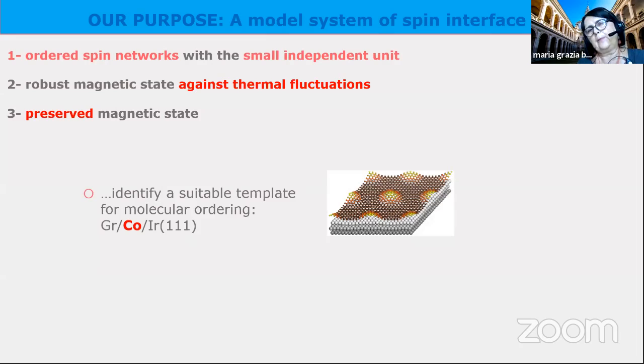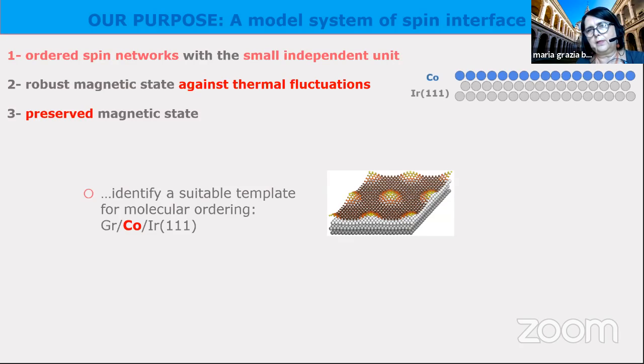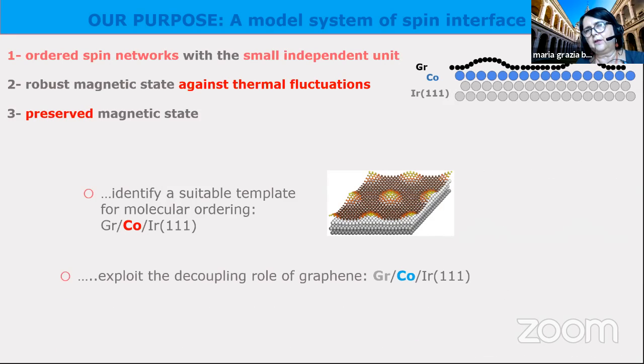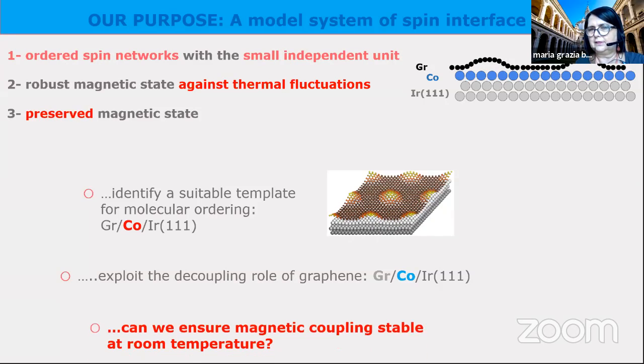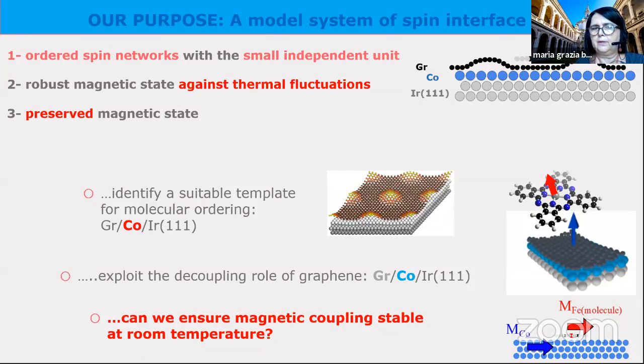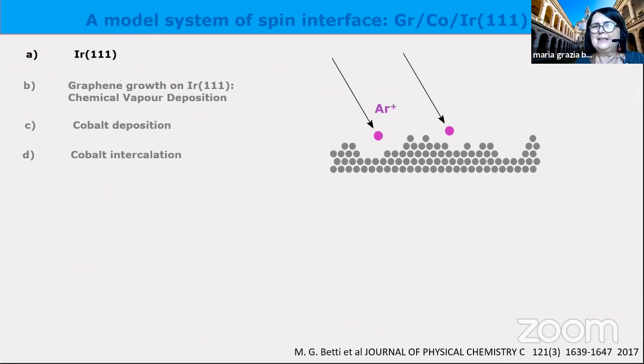So we identify this template. This template is constituted by a substrate of iridium where we put graphene on, and then we intercalate cobalt. We would like to exploit the decoupling of graphene as a spacer, under the cobalt and the molecule that we put on. So now the question is, can we ensure a magnetic coupling between the molecule and the cobalt, are they close enough to be magnetically sensitive to each other? And I would like to show you our results.